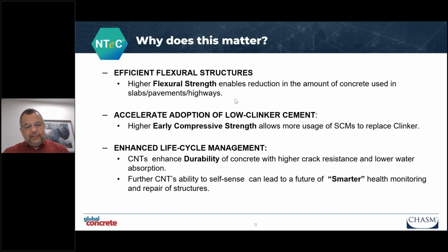The second element is to enhance the early compressive strength, which will remove the barrier of some of the SCM adoption which you're seeing. And then there are certain further things which are well studied: durability of concrete really improves with very little nanotube due to porosity reduction, crack resistance, and so on and so forth. And now you have the element of smarter health monitoring, which is a futuristic view, which by the way today is proven in universities, where nanotubes display a piezoelectric property, which will allow us to self-sense the stress and state of damage in a concrete at any point in time.